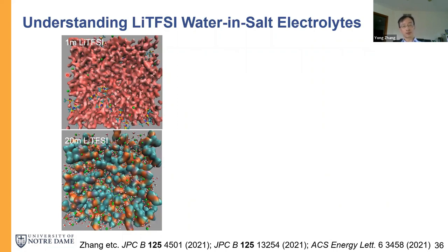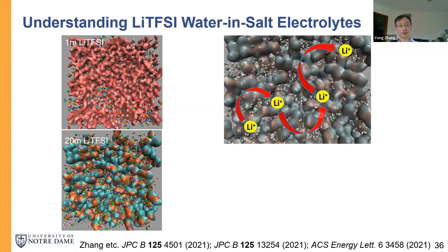So just to summarize everything I mentioned today. We focused on these lithium TFSI water-in-salt electrolytes. At low concentration, we see a water network. At high concentration, that is replaced by a homogeneous LiTFSI water network, and water and lithium are distributed in that framework. For the dynamics, it's really a hopping mechanism instead of vehicular, as suggested by previous studies.